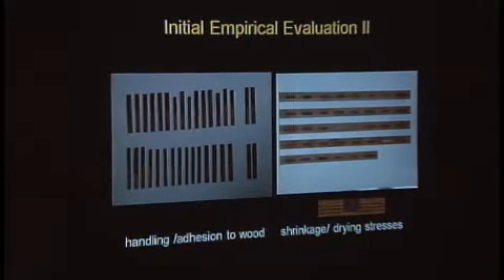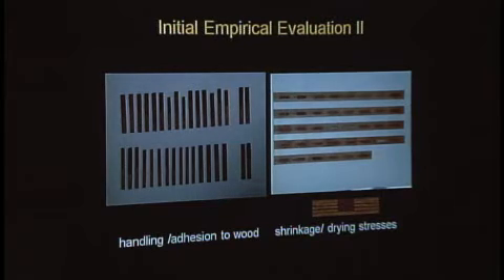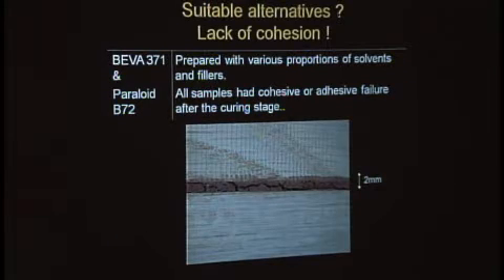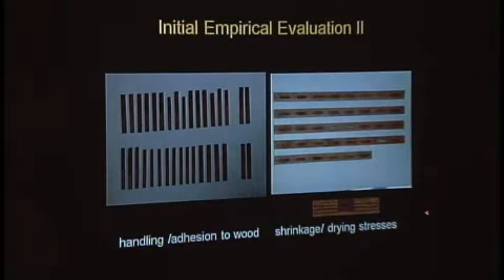And then, all importantly, drying stresses within a structure, looking first at how they dried in plane and out of plane, and how they might pull up if you had a thin balsa here instead of the gesso, to see what would happen if you pulled up as they dried.